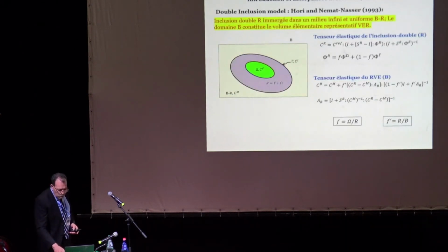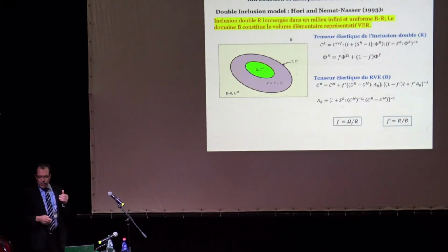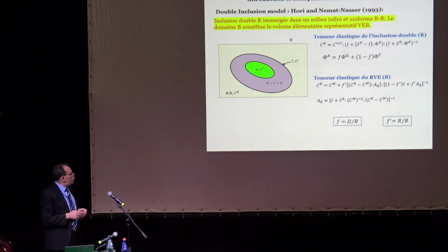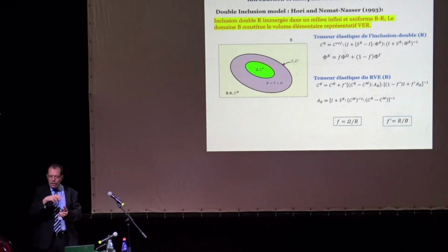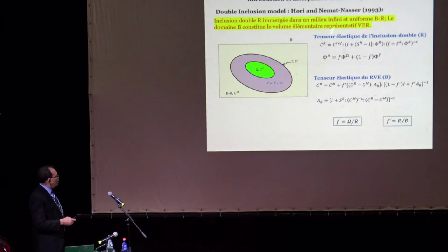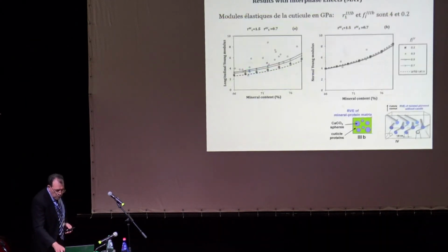What we decided to do is just to see if we can do something at these different levels, at level 3 and level 4, and include some interface, okay? Some jump, instead of having a jump between the properties of the filler and the matrix, we'll have an interface that has some intermediate properties and so on. And we used the double inclusion model that I mentioned before, which was initially developed by Hori and Nemat-Nasser in 1993. And again, these are the relationships and so on. I'm not going into these details. By doing that at this level and at this level, this is what we did, okay? And also at this level here, okay? At this level.